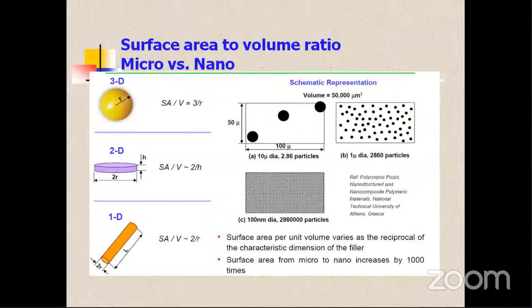So this is the slide where you can visualize how nanoparticles are beneficial in the development of nanocomposites with very low volume, like 0.5% carbon nanotubes will give optimized properties, whereas to achieve the same strength, if you use carbon fiber, you may need to go for 68% of carbon fibers to get the same properties. For any organic or inorganic filler, particle shapes are different. Some particles are spherical, some may be flakes, a two-dimensional structure, or others like carbon nanotubes, a one-dimensional structure.